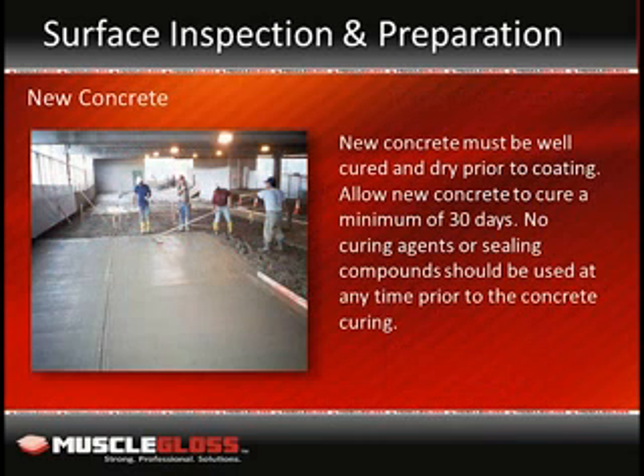New concrete must be well cured and dry prior to coating. Allow new concrete to cure a minimum of 30 days. No curing agents or sealing compounds should be used at any time prior to the concrete curing, after which any oil, grease, or other foreign material must be removed. If you seal or epoxy concrete prior to 30 days, there is a chance you will be sealing in some of that moisture and hence weakening the integrity of the concrete.